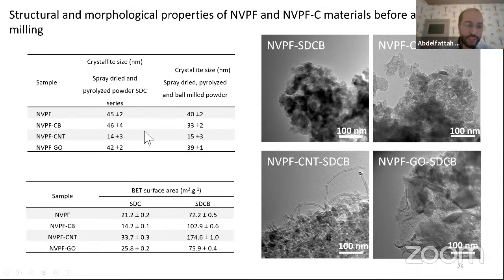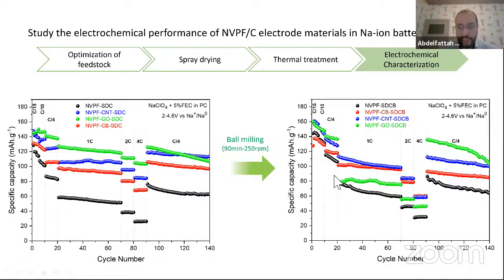We have also some differences, not only in morphology, but also in the surface area, because we make some BET surface measurements. And after grinding, we had some surprising results, mainly for the one with graphene, because the capacity decreased at 1C. Why? Because we are making the grinding. Here we make the measurements versus the sodium. When we are making the grinding, we are breaking these graphene sheets, which means that we are inhibiting their positive effect, and the performance decreases.